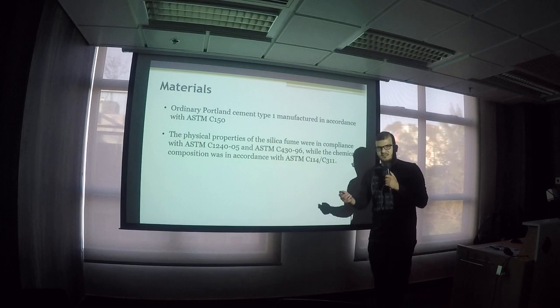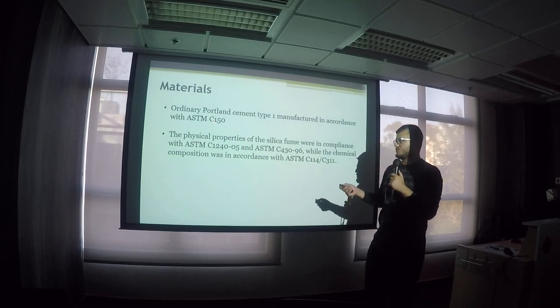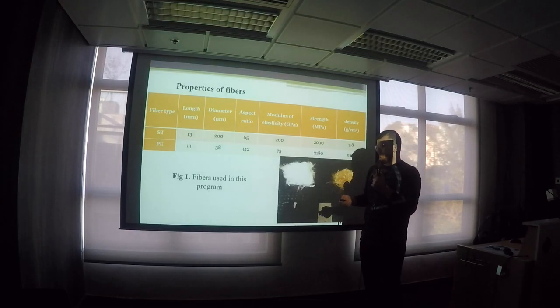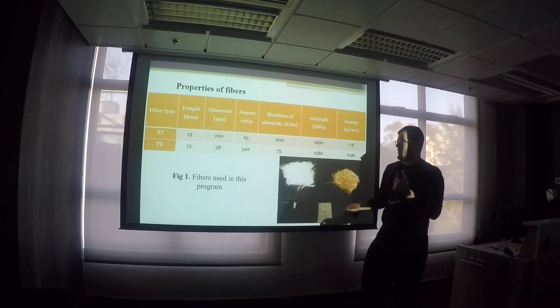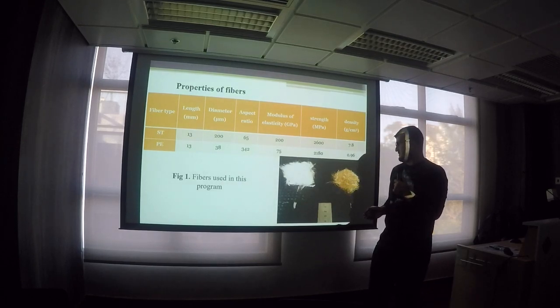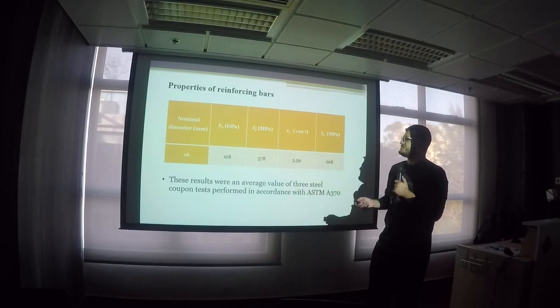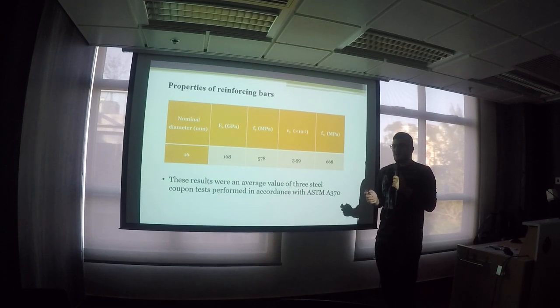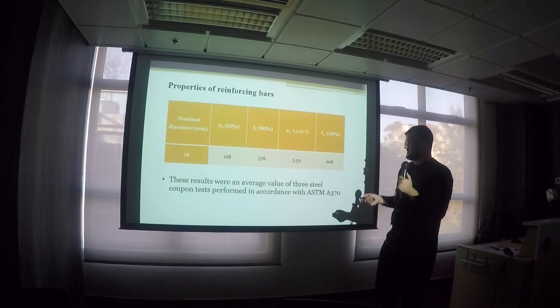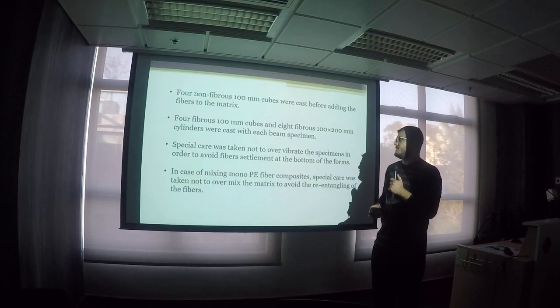The materials used in this research were in accordance with ASTM in every aspect. And here are the properties of the fibers, as you can see, and here is the picture. This is the steel fiber, and this is the polyethylene fiber, and they have almost the same length. The reinforcing steel bars used in the beams were also tested under ASTM.